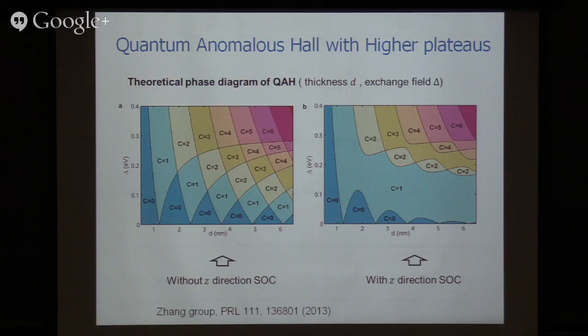So you may think that this is analogous to the quantum Hall effect. I change the magnetic field, I go to different plateaus, but they go in the opposite direction. If I increase the magnetic field, I go to a lower conductance plateau. By increasing the magnetic field, I increase the degeneracy of the Landau level, and actually I go to a lower conductance plateau. In this quantum anomalous Hall system, where I increase the magnetic moments, it goes to a higher conductance plateau.